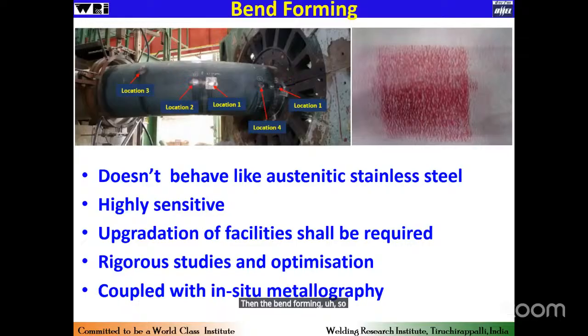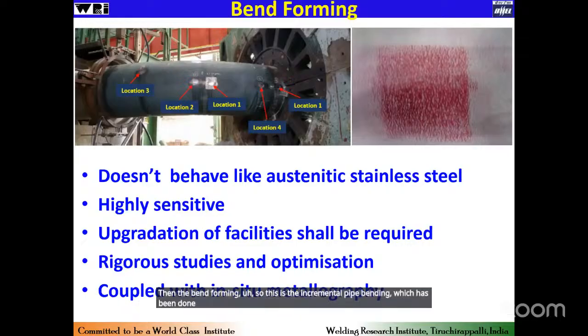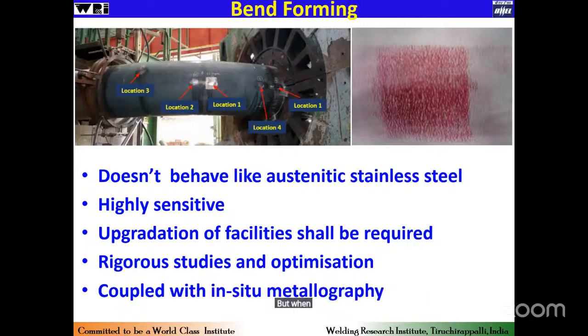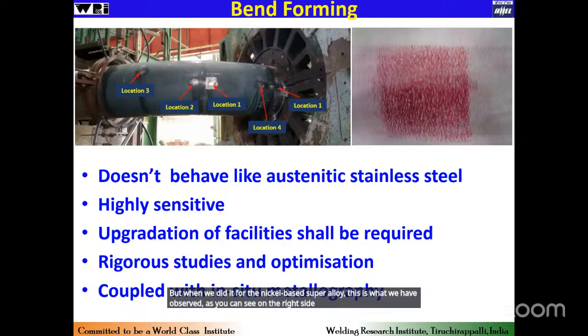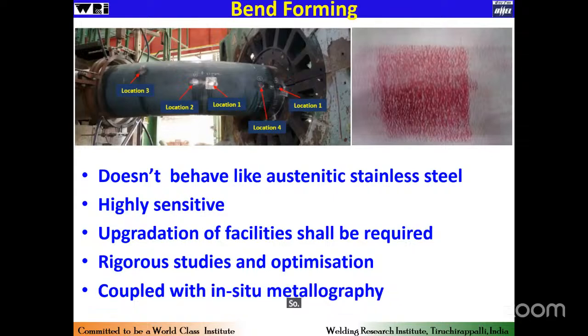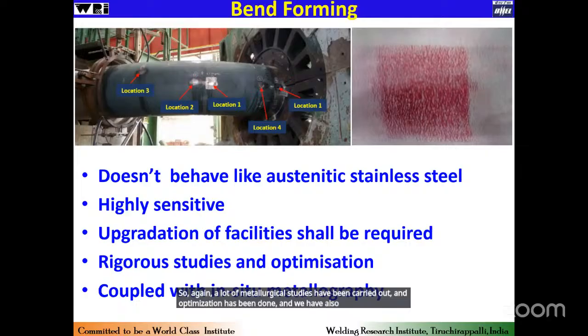So this is the incremental pipe bending, which has been done conventionally. This has been in practice, and we have been using it. But when we did it for the nickel-based superalloy, this is what we have observed. As you can see on the right side, it has cracked at the surface. So again, a lot of metallurgical studies have been carried out and optimization has been done, and we have also had a number of discussions with the material supplier to understand the reason for these kinds of defects. So that when we have addressed the root cause, we are able to overcome this issue. And what I am trying to convey is, it was not a simple task at every stage.